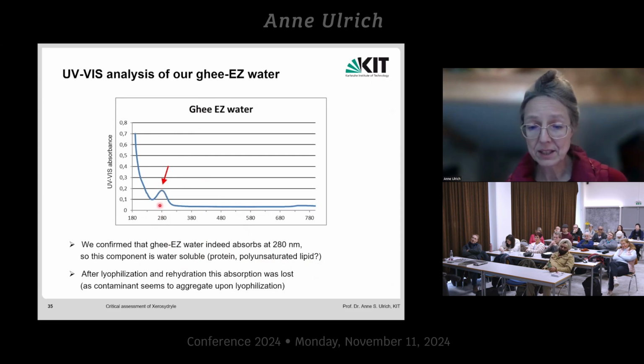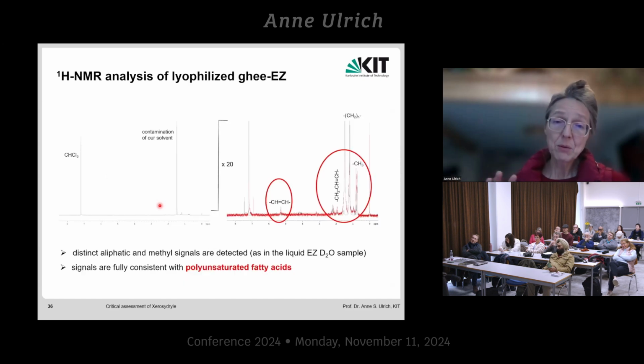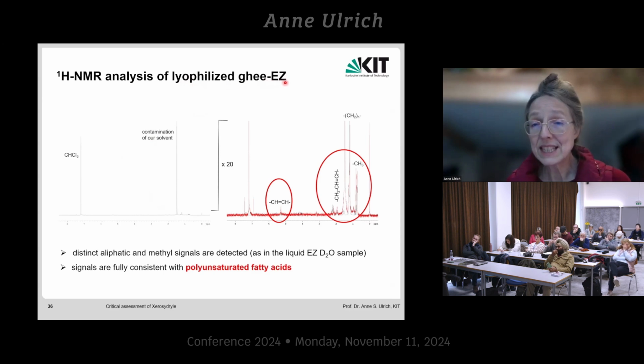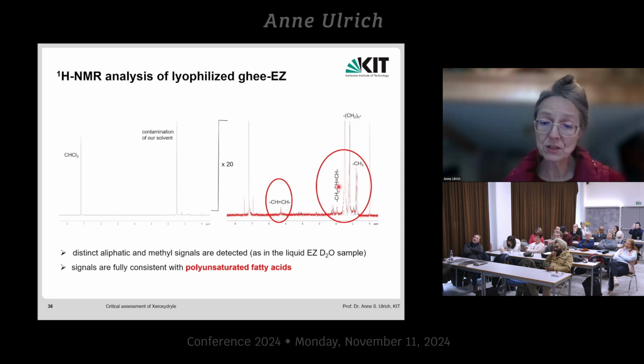This is also something that was written in the paper. But now, without going into the NMR analysis, we did all the reference spectra, also in deuterated solvents, to look for the proton signals, etc. And we prepared our lyophilized EZ sample. And you see here a small interesting set of signals, which when we enlarge it, shows that this extracted water from the surface of ghee contains lots of unsaturated methylene and methine groups, which are characteristic of lipid acyl chains, especially of polyunsaturated lipid chains. They seem to have been enriched in the EZ layer on the surface.